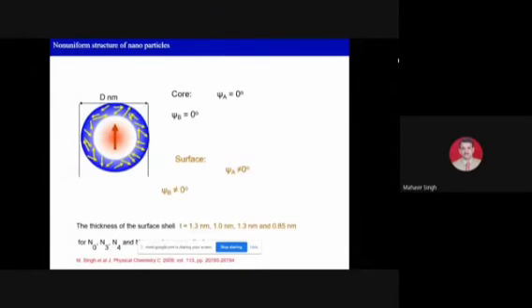At the center, this is the core. At the surface, this is the disorder. So we calculate the disorder thickness. How much is the disorder at the surface? So when we move from bulk to nano, how much is the disorder? We can calculate through Mossbauer spectroscopy and field data, and we can also calculate by Langevin function, using SQUID data. So we use SQUID data to fit the Langevin function.